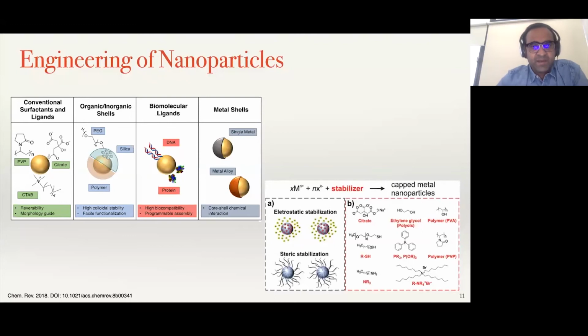So this was an example where I talked about how the nanoparticle surface is very important, because I can have specific ligands which are associated with these particles. So for example, if you look at the first figure, I have a gold nanoparticle, and I can create it by having a citrate capping, a polyvinyl pyrrolidone capping, or a CTAB capping. All these three cappings are going to have a very different response. Even though my particle is gold, by changing the surface chemistry, I'm getting very different responses from the same gold nanoparticle.